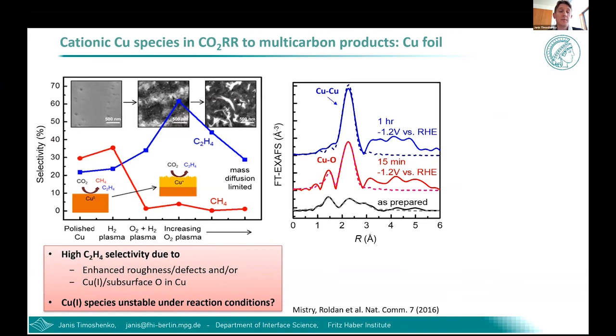So it means that on top of these morphological changes which we induce in our catalyst by plasma treatment, also the presence of oxides, similarly induced by the oxygen plasma treatment, can be important for understanding the catalytic properties. And X-ray absorption studies can provide additional important information about the stability of such oxide species.